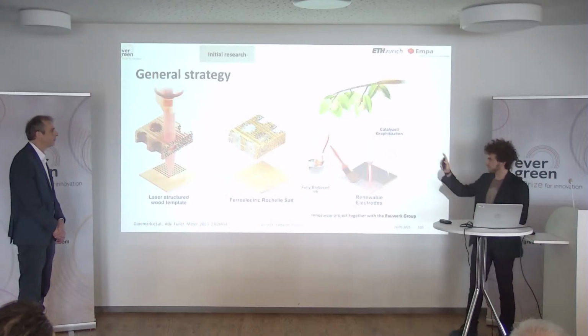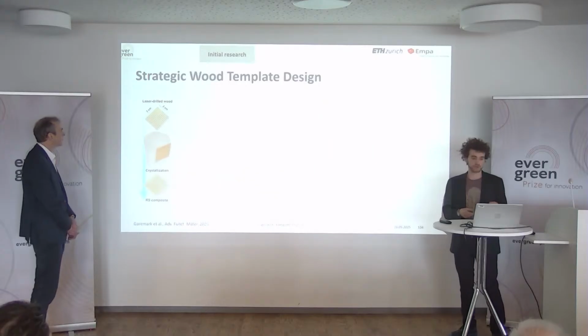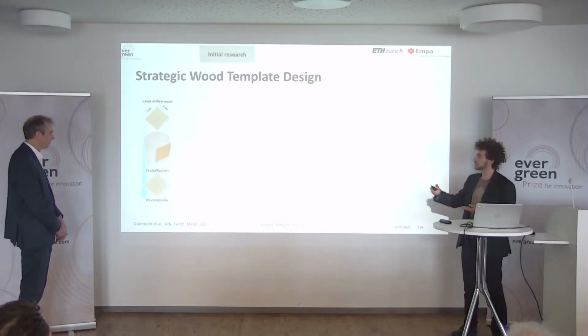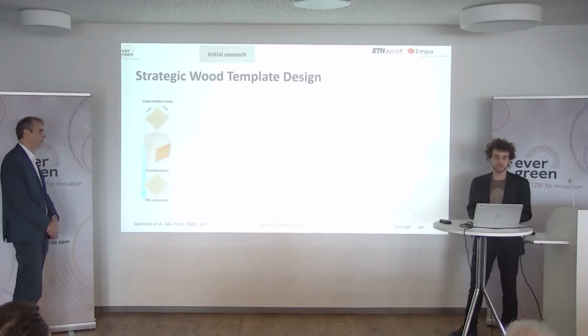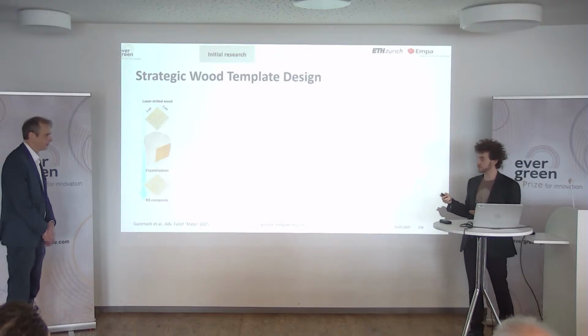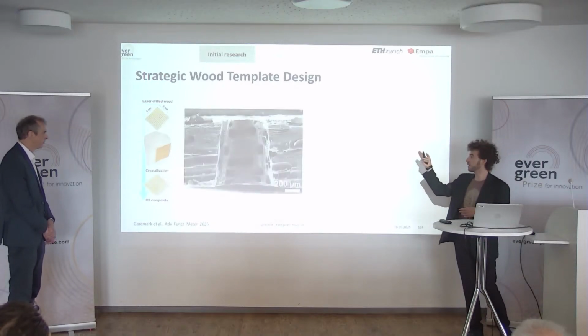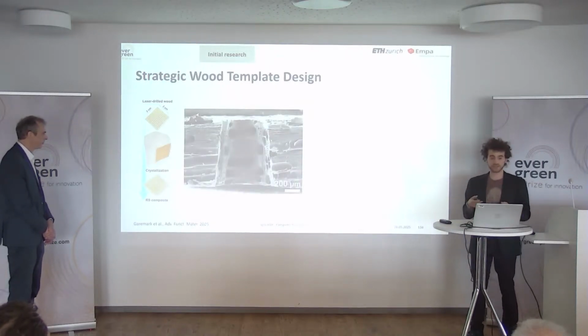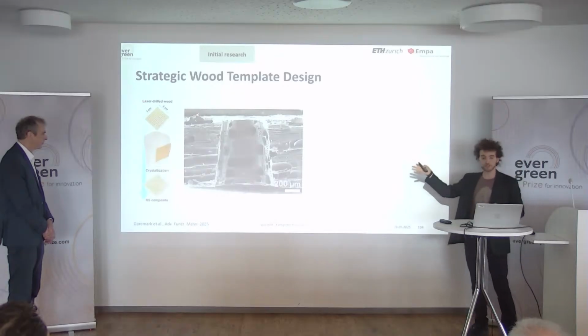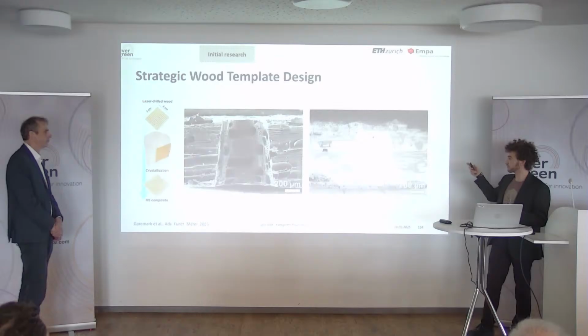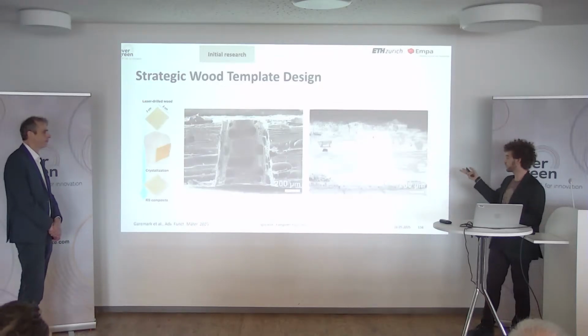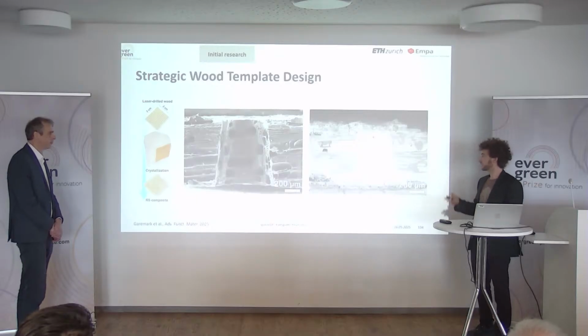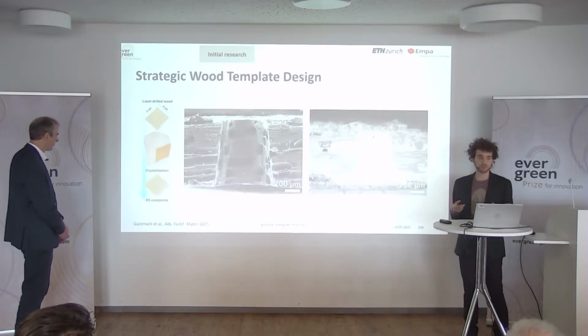And if we look back at the second step, more strategically at how this crystallization works, we can see that the laser drilled wood allows, first of all, for a very porous structure that we create. Then we use the hierarchical porosity from wood to grow the Rochelle salt through the wood template, and we have a very good interface between the Rochelle salt and the wood. This allows us then to overcome the brittleness of Rochelle salt, as we explained.